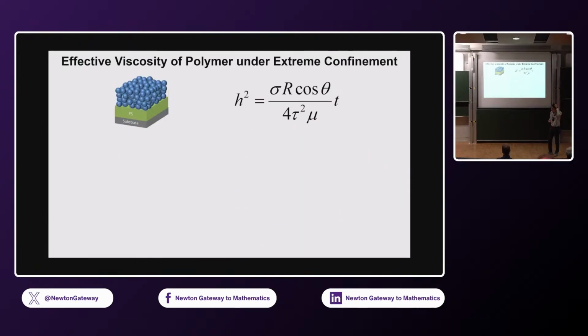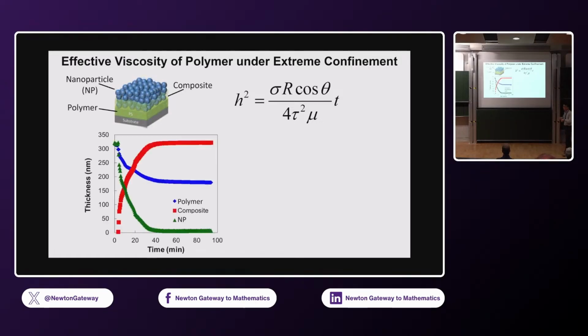So how do we monitor the dynamics of this process? It's actually very easy. Okay, we take our bilayer. All of the particles that I'm going to show you are silica, and the polymer that I'll be featuring a lot is polystyrene. Okay, we take this bilayer and put it on a hot stage, take it to an ellipsometer, and then we heat it. When you heat it, the polymer undergoes capillary infiltration. Okay, and then we can monitor the thicknesses of these 3 different layers: the empty nanoparticle layer, the composite layer, and the polymer layer. Okay, so this is what it looks like.